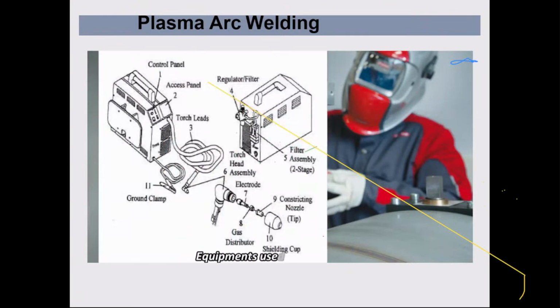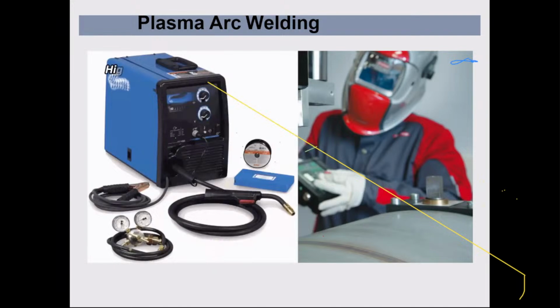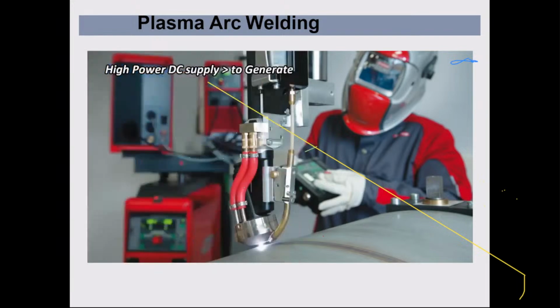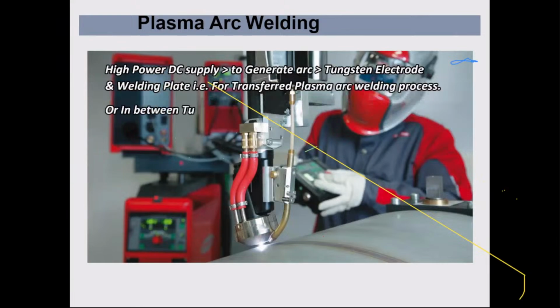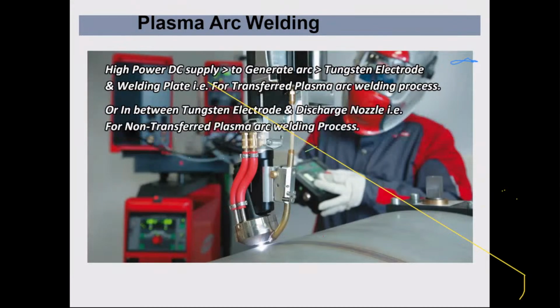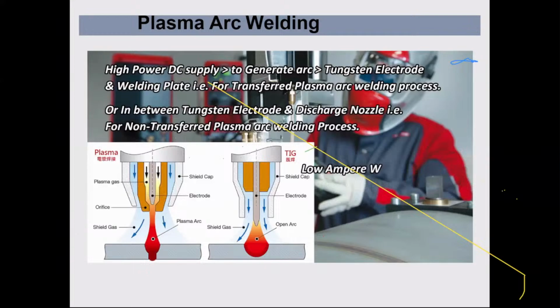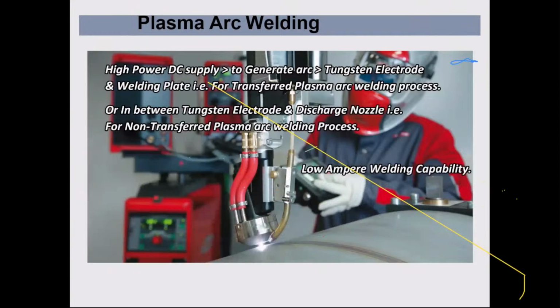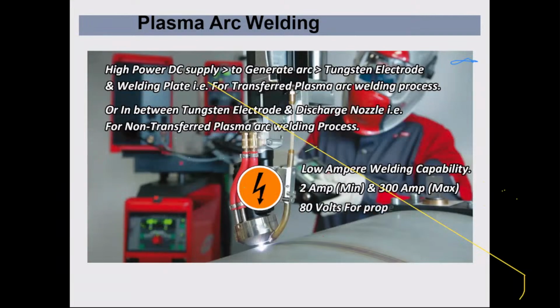Now let's check out the equipment used in the process of plasma arc welding. The plasma arc welding process needs a high-power DC supply to generate an electric spark between the tungsten electrode and the welding plates, for the transferred plasma arc welding process, or between the tungsten electrode and the discharge nozzle, for the non-transferred plasma arc welding process. One of the main features of plasma arc welding which makes it different from TIG is its low ampere welding capability. This welding can weld at a low ampere of about 2 amperes, and the maximum current it can handle is about 300 amperes. It needs about 80 volts for proper working.